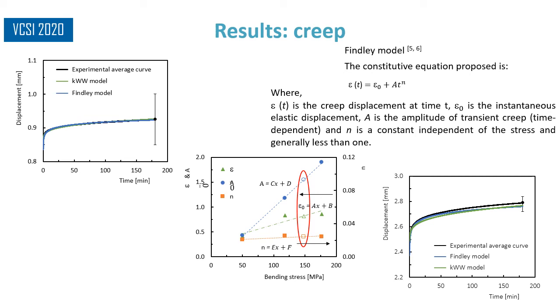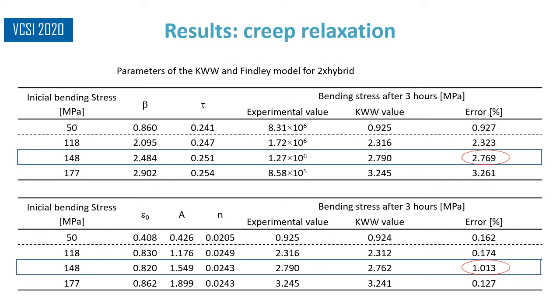In this study, we also applied the Findley law, which is widely used to describe the creep behavior of composite materials. This method of applying the model is similar to the previous one, and in the graphs it is possible to compare the behavior of the two models. The table shows the parameters calculated and estimated by both models for the different study stresses, as well as the theoretical and experimental value after 3 hours and their errors. Also, in this case the errors of the applied models are low.